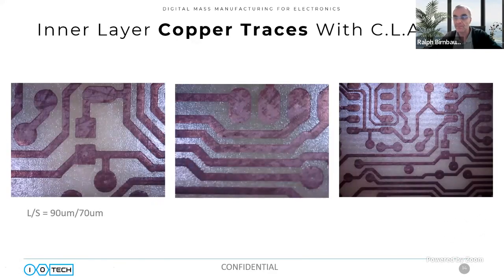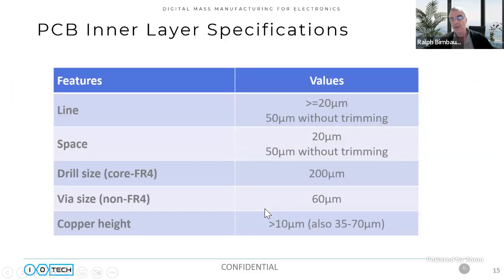So here are some lines that we've printed with this technology. These are not especially fine lines, these are 90 micron lines, but you can see how smooth the edges are. So as I said, we actually print 20 micron lines, but without trimming it's 50 micron.